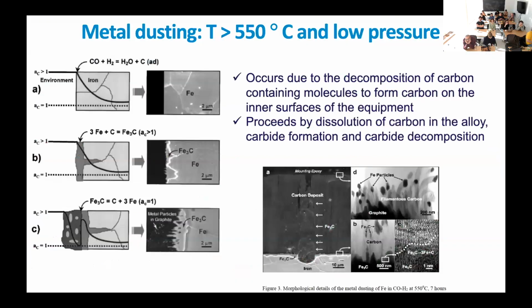okay? This is a problem that was brought to us by industry. We worked with Shell, the Research and Development Center in Qatar, and also Shell in the Netherlands. What happens is that when they operate their equipment at a temperature around 550 Celsius and at low pressure, they notice that there is decomposition of carbon-containing molecules to form carbon on the inner surface of the equipment.